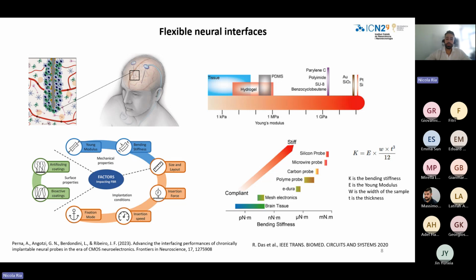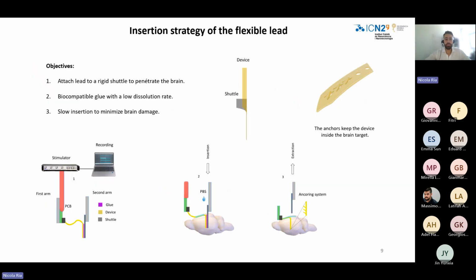But there is also another requirement, that is the fact that these devices have to be inserted inside the brain, so they need to have enough bending stiffness to penetrate the brain tissue. For this reason, just for the insertion of the flexible lead, we temporarily glue the flexible device with a rigid shuttle made by silicon. So once the insertion is completed, the glue that is biocompatible and dissolvable by applying PBS is dissolved, and the shuttle is removed, leaving inside only the flexible lead.